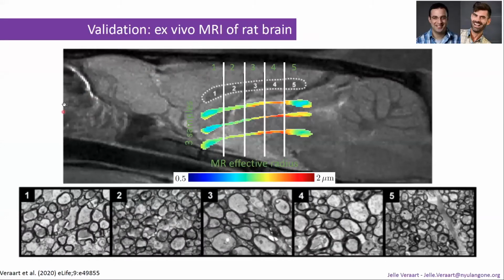The accuracy has been assessed in a preclinical study in collaboration with Noam Shemesh and Daniel Nunes of the Champalimaud Foundation in Lisbon. And there we scanned perfusion-fixed rat brains, three of them. And we focused on the mid-sagittal plane, focused on the corpus callosum. And just over here on the three maps, I show the effective MR radius along the corpus callosum, and you can see this beautiful low, high, low trend that is well known from literature in rodents, but also in humans. So that's a qualitative assessment of accuracy, or gaining confidence in this technique.